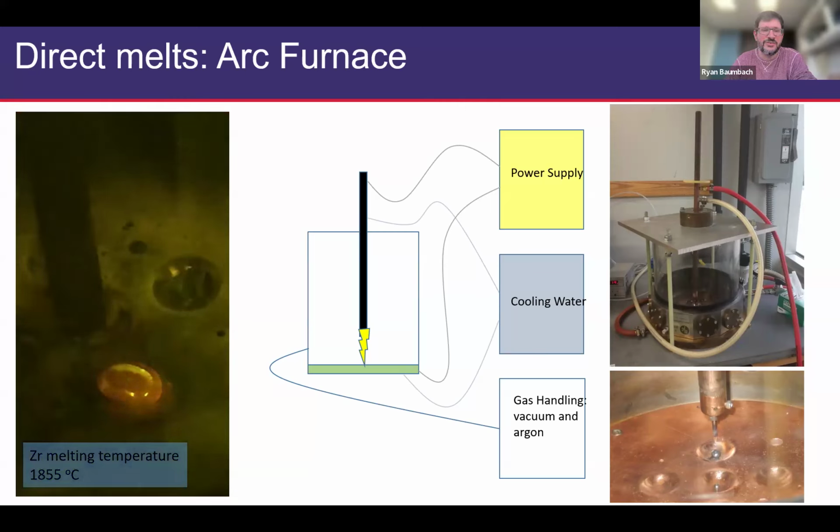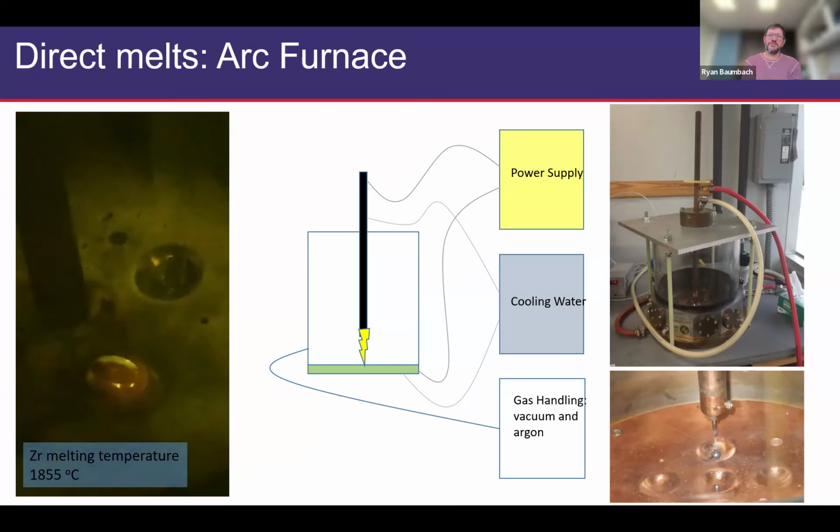But what is completely uncontrolled here is the cooling rate. And that cooling rate is really very fast. So generally speaking, your expectation would be that you can access a congruently melting phase, but that you would not produce large single crystals. Okay, you're probably going to produce polycrystals out of this. But one additional hint is that for some materials, even though it's a polycrystal, you can cleave out appreciably sized grains that sometimes are effectively single crystals and are reasonably high quality. So that's sort of a poor man's way of obtaining single crystals of materials that form at really high temperatures.